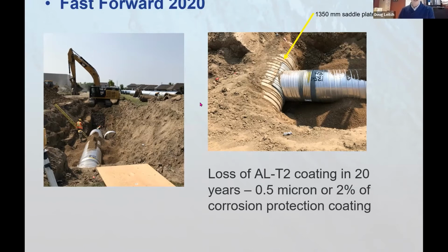And he did some magic with some of his testing and basically found that after 20 years, 0.5 microns of the coating were gone, or represent about 2% of the corrosion protection. So basically, we still have over 90% corrosion protection left in that main sewer line after 20 years.